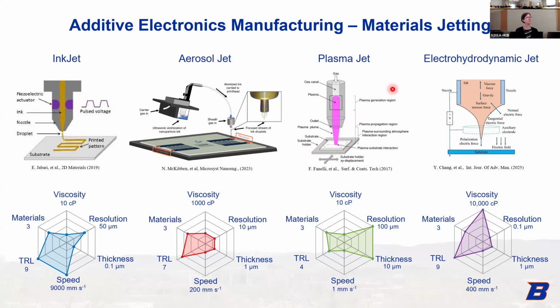And electrohydrodynamic jet, we've worked a little bit with this, but I think some of the leaders in this are at Michigan and Illinois. But it works a lot like inkjet, where you have your print head, but you apply a high electric field between the nozzle and the substrate. That results in the formation of a cone-shaped jet, which can print down into the tens of nanometer resolution. So you can look at the spider plots to compare quickly the different metrics of these printers.